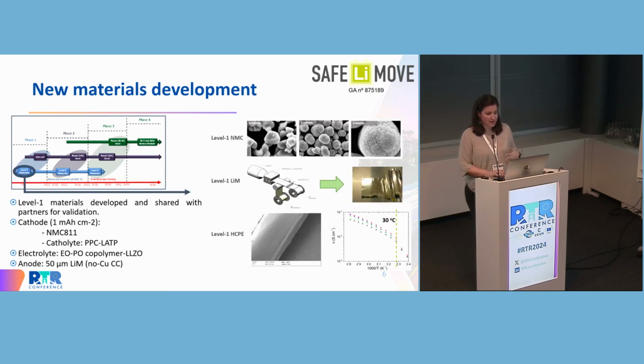So starting from the very beginning, level 1 materials, as I was saying before, were selected. So NMC type cathode active material. Then we decided to use a hybrid catholyte. So in this case, our binder was a conductive polymer electrolyte, where we were combining again organic and inorganic phases. Then for the electrolyte, we had another type of polymer and another type of inorganic filler. So mainly we wanted to design ad hoc electrolytes or layers to be in contact with lithium metal and to be in contact with the cathode, because at the end we need to consider that the requirements of the lithium metal are not the same as the requirements of the cathode. And then the last component, the anode: we used a self-standing lithium metal with no copper, of 50 micrometers.